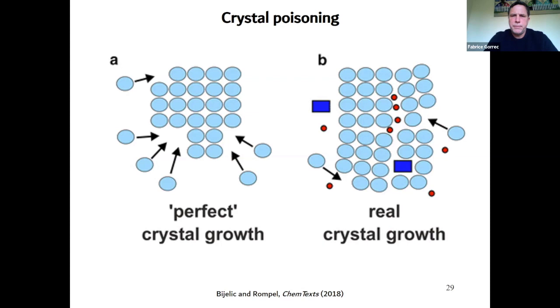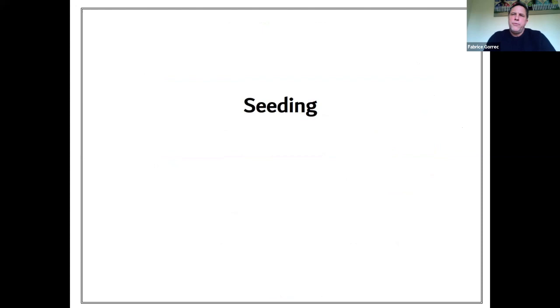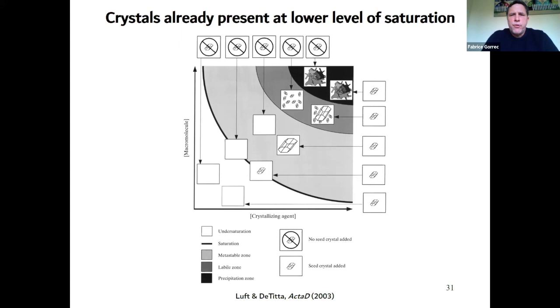If you remember the solubility phase diagram, the ideal zone of saturation for growing crystals is a lower saturation than where they nucleate eventually. So a way to optimize this is to use seeding. So basically you will use the crystals that you obtained previously, and then you put them in the new experiments. This way, you already have crystal presence when the experiment reaches the metastable zone. And it's a way to optimize crystal growth. It also helps to break the energy barrier of nucleation. You need to obtain crystals first to do this. So that's an optimization that you do when you have crystals.